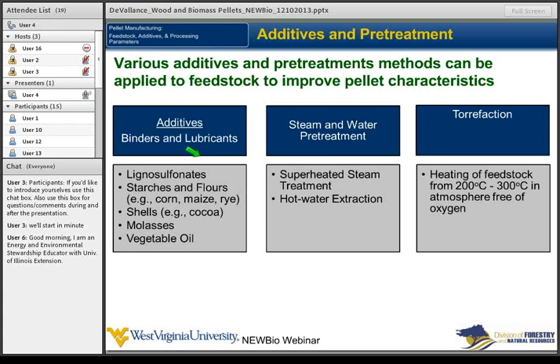The next section in terms of processing is we take these particles that have been dried and treated and start adding additives to them. The first one, if we need to, is some kind of binder: lignosulfonates, starches and flours, shells. We can add some molasses in some cases. Vegetable oil mainly acts as a lubricant. It helps us reduce the energy it takes to force that material through a die.